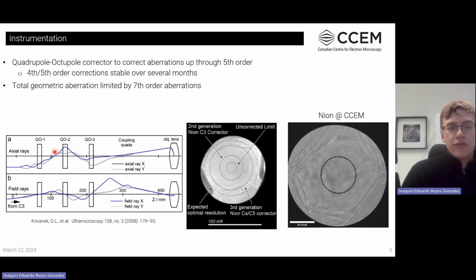The important part about this specific corrector is that it's allowing you to correct these fourth and fifth order aberrations. Typically, in TEMs and STEMs, the fifth order aberrations are going to be set in the factory. You'll receive your TEM and you won't be able to adjust those fifth order aberrations. You will be able to correct up to the fourth, maybe every few months or so, but those fifth will be just set. The only people who can touch those are service, and they will not touch them really because those fifth are normally just set in stone.